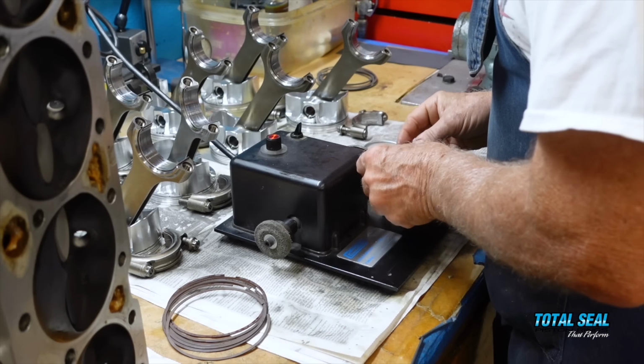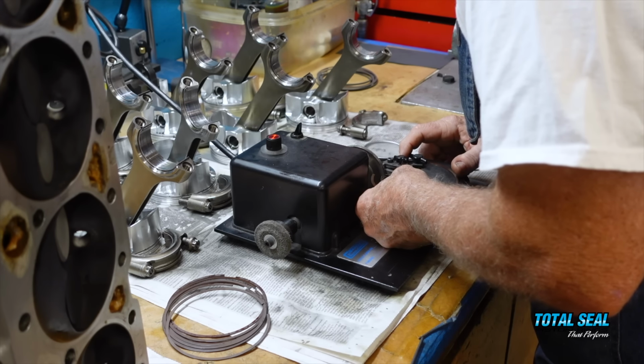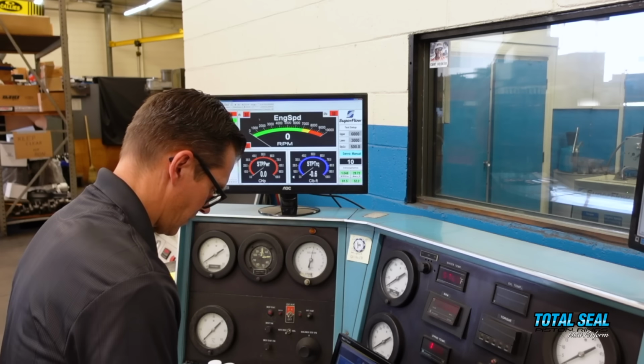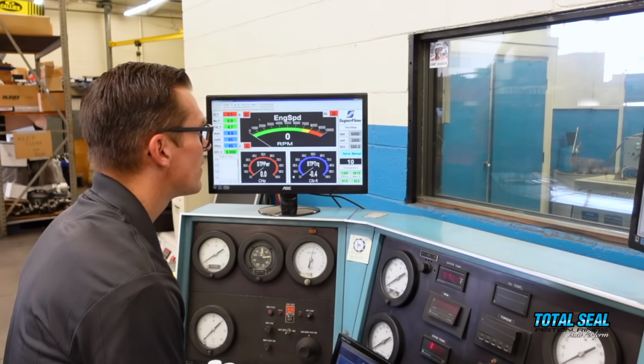Again, we mentioned it earlier, not only did we change the size, our change in size is less than theirs, but we're adding gas ports and we honed it for the modern steel rings. Let's see if adding the gas ports and changing the hone overcomes the lack of thickness change compared to the Engine Masters test. Ignition. Fire in the hole.